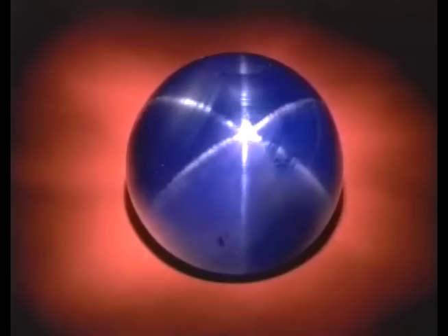And as it does that, the larger titanium atoms start feeling kind of snug, kind of tight in that corundum crystal. And the way they get around that problem is all the titanium atoms come together to form their own crystal of another mineral inside of the corundum crystal. So we end up with rutile crystals, that is titanium oxide inside of the corundum. These rutile crystals are long needles or fibers, and because of the symmetry of the crystal structure of the corundum, those rutile needles are forced to line themselves up in one of three directions. And we have, therefore, three sets of very fine rutile needles oriented inside the corundum crystal.